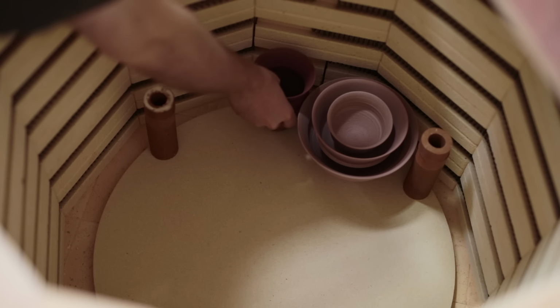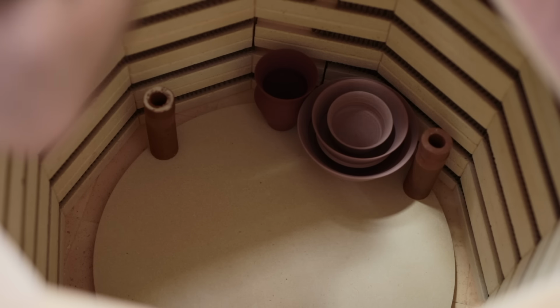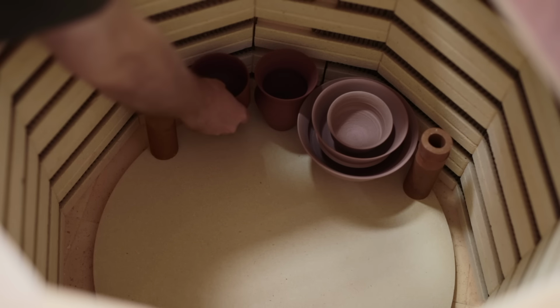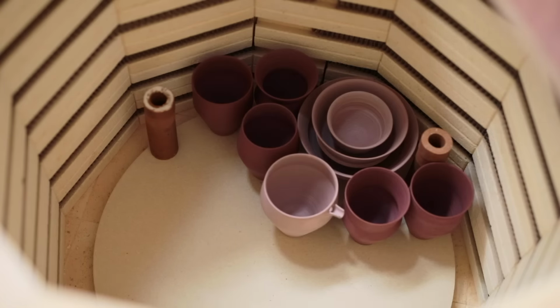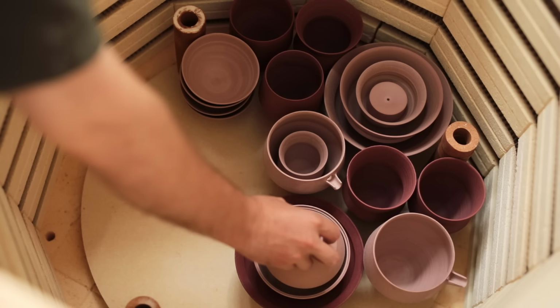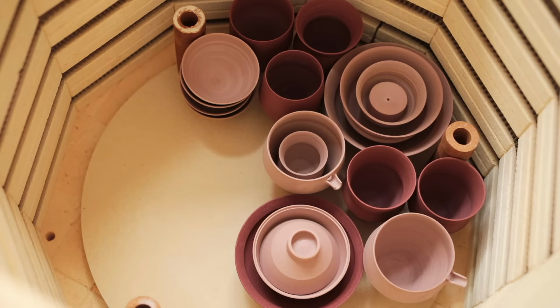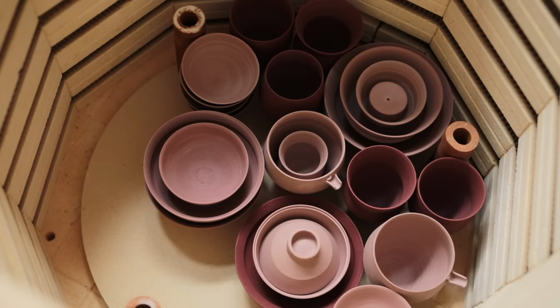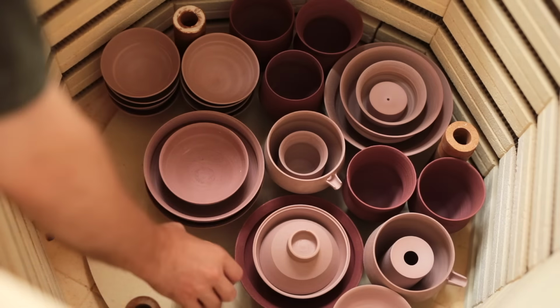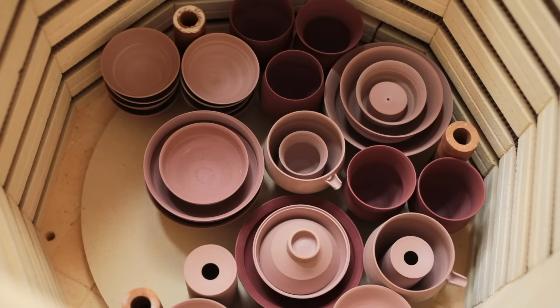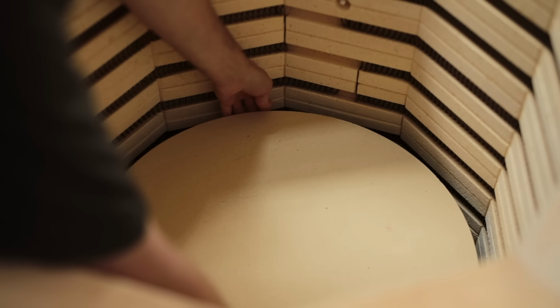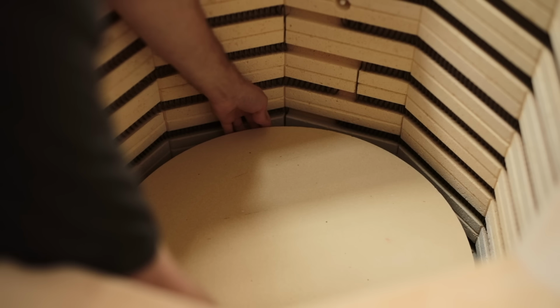For this firing to 1000 degrees Celsius, the pots can touch. In fact, the denser the pack, the better, as it makes each firing more cost efficient. This kiln is fired automatically following a program I set. It's heated by elements in the walls, much like you'll have in a toaster, although these ones are much more powerful, and once the kiln has been fully packed, there's a lid on top which can be closed, which traps all the hot air in during the firing.